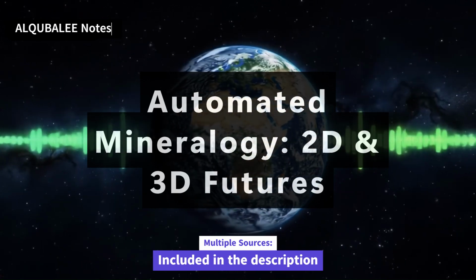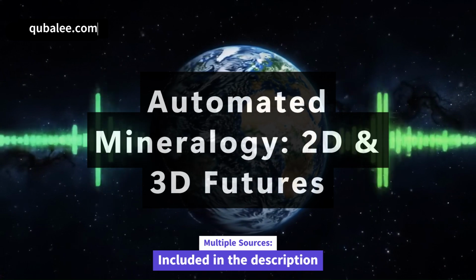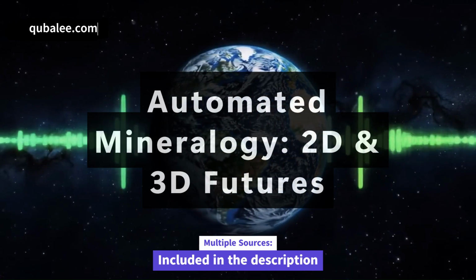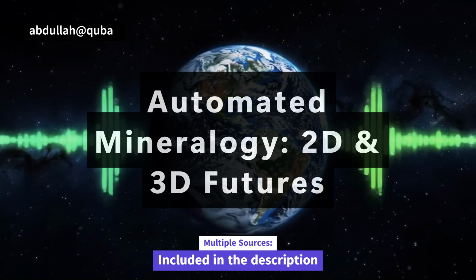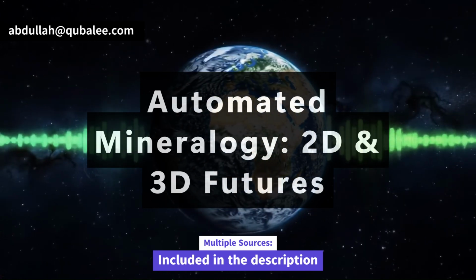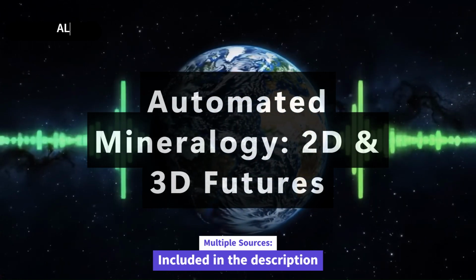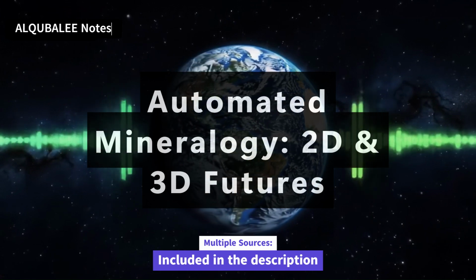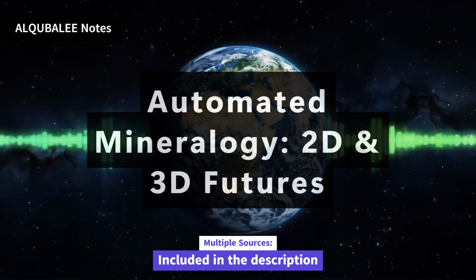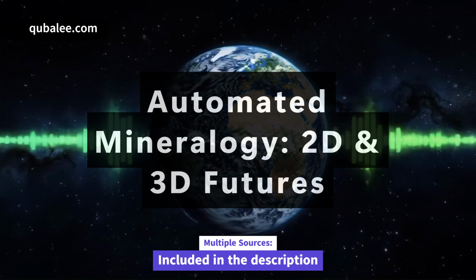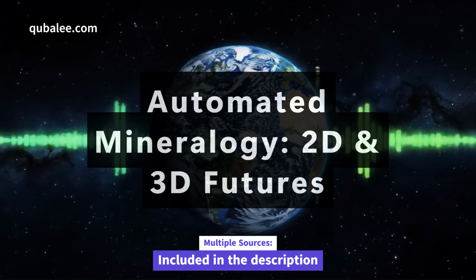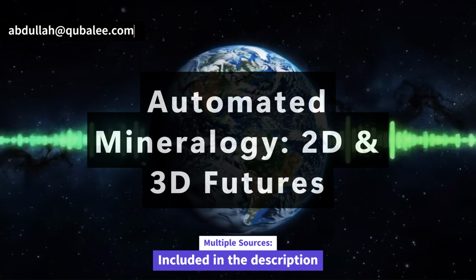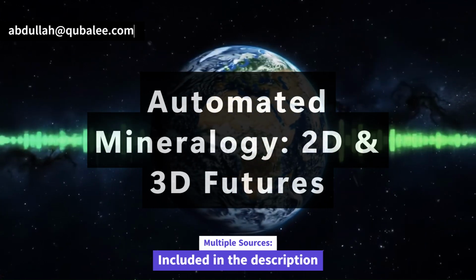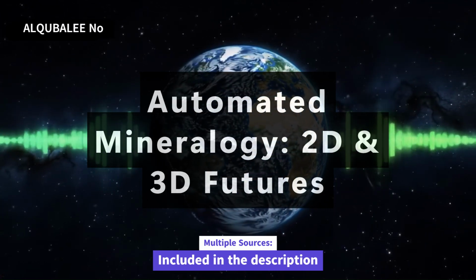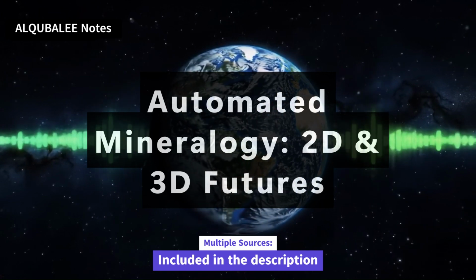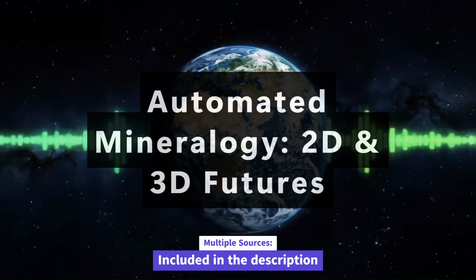Okay, so you get the big picture view, but you said it keeps the high resolution. How detailed are we talking across that whole large map? The resolution can be really impressive. For the imaging part, like the backscattered electron image or BSE, you might be getting resolutions down to, say, 100 nanometers. Wow, okay. For the actual EDS chemical measurements, the step size between pixels might be on the order of microns, maybe even finer depending on what you're looking for and how much time you have. You can tailor it. It sounds like you end up with this incredibly rich spatial data set.